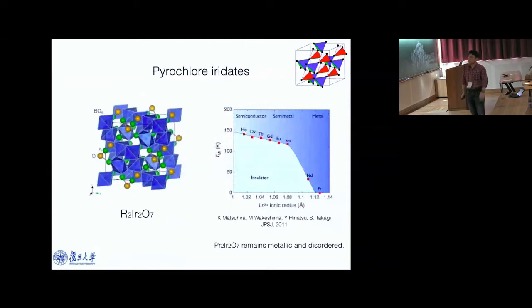So now we turn to this family of materials, which is called the Pyrochlore iridate. This is actually a natural place to study the interplay between strong correlation and strong spin-orbit coupling. In other words, strong topological phenomena in the presence of strong correlation. In this family of materials, both the rare earth and the iridium atoms form a lattice called Pyrochlore, which we have seen many times in this workshop. And if you vary the rare earth atoms, because there are so many rare earth atoms, you can change the rare earth atom from holmium, dysprosium, terbium, gadolinium, europium, and to praseodymium.